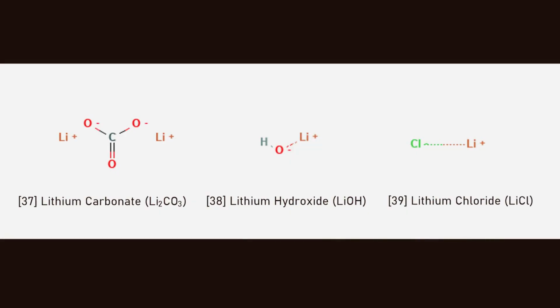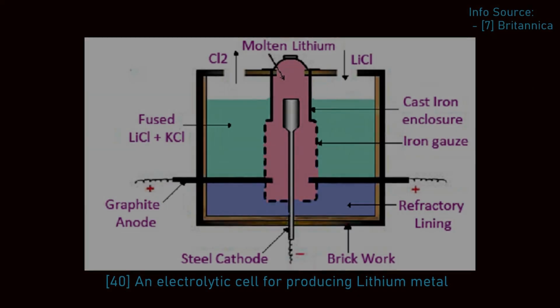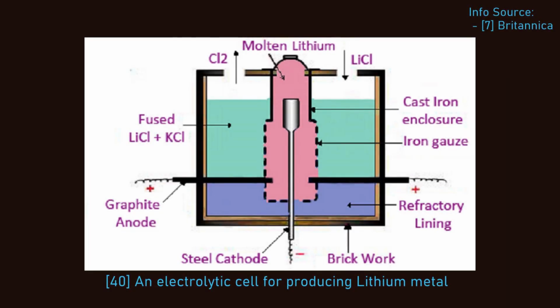Many lithium products are made from its carbonate, hydroxide, and chloride forms, but some materials still require the actual metal. To get it, lithium chloride needs to be electrolyzed. To produce the metal, lithium chloride is mixed with potassium chloride before being electrolyzed. The electrolyte contents of a cell are heated so that the salts melt and become a liquid. The lower melting point of this mixture, at around 400 to 420 degrees Celsius, compared to pure lithium chloride at 610 degrees Celsius, reduces the amount of energy required to perform the process.